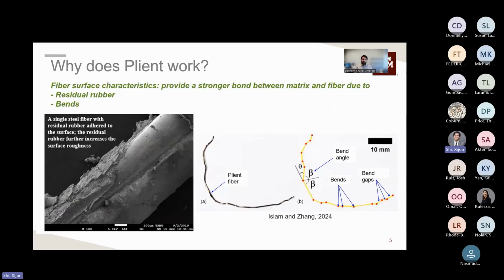So the first reason is because of the recycling process, there is some residual rubber that remains on the surface of the fibers. And there's a really good image shown on the left there, showing a zoomed in image of the fiber, and you can see the surface of the fiber is coated with some residual rubber. What this residual rubber does is offer a texture to the fiber that improves the bonding between the fiber and the surrounding cement matrix.